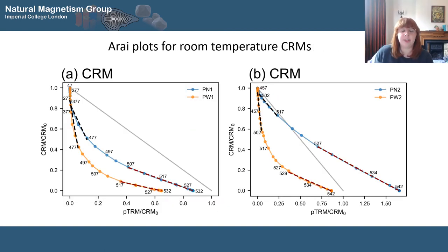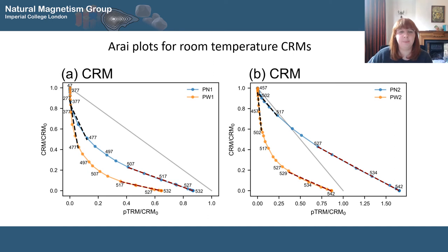Since we're interested in how CRMs contribute to paleointensity estimates, we looked at how CRMs would behave during the Thellier paleointensity determination method, and we looked at their Arai plots. As you can see, these CRM Arai plots are curved, and the degree of curvature increases with interactions and with a decrease in coercivity.